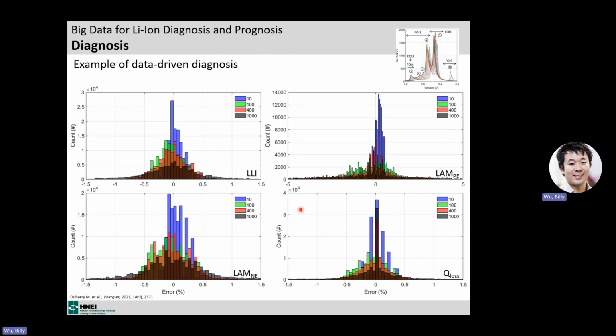And so once we have that, now we can start to see if methods work or not for diagnosis, and if they work on every possible combination. So here's an example of our diagnosis method when we track different features on the curve. And we did it for the 100,000 duty cycles at cycle 10, 100, 400, and 1,000. And that's the error in the estimation of loss of lithium, loss of positive, loss of negative, and capacity loss. And you can see that for our method, the error is extremely small for all 100,000 different duty cycles.